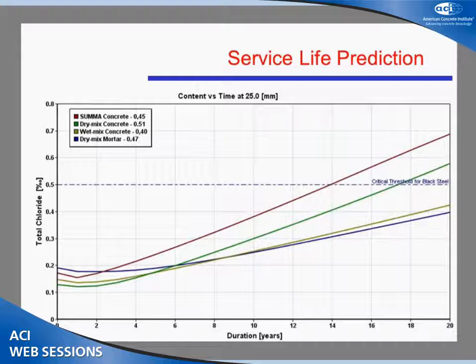Essentially, you can see here that according to the simulation and the exposure, considering both the chloride content I just mentioned and the humidity, you can expect about 14 years of service life, rather 14 years before you hit the critical threshold, a critical threshold we chose for black steel, followed also by the other mixes which follow shortly after.